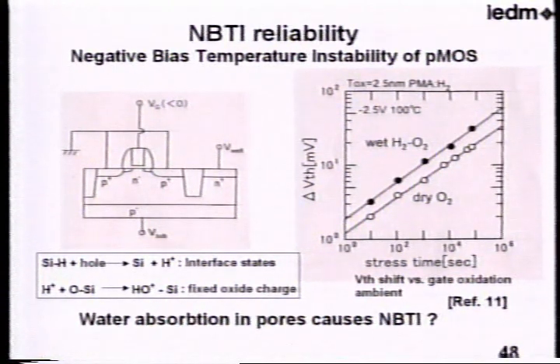The mechanism of this kind of increase is not clear at this moment, but people believe some hydrogen forms some interface state with a combination at the interface of gate oxide. And this will make some fixed oxide charge in SiO2. If we adopted porous low K into their devices, the poor water absorption is a very big concern. And if the hydrogen in the film is diffused into a device, there is a concern to make this kind of negative bias temperature instability. This is the future work.